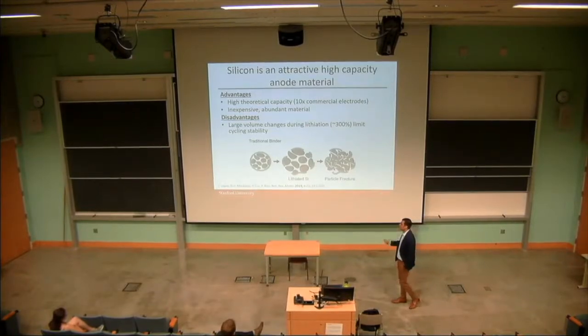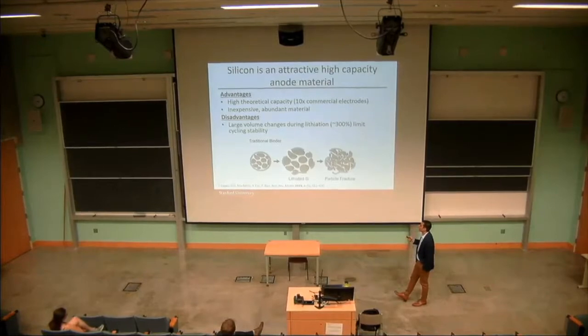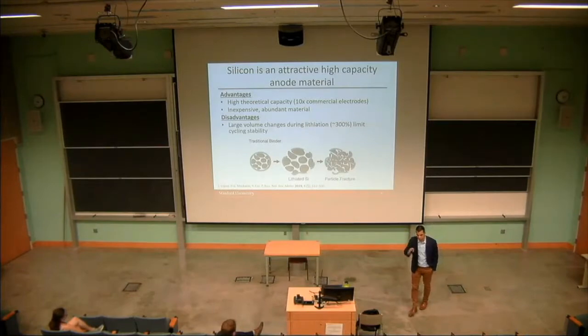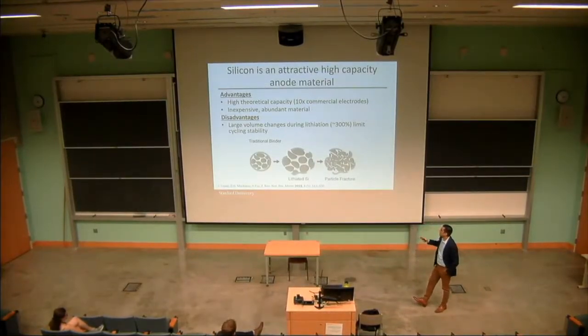Unfortunately, and the reason we're not already using it today in high quantities is because it has extremely large volume change. So silicon goes from just pure silicon, and it forms an alloy with lithium with about 3.5 lithiums per every silicon atom. But when it does that, it also goes through about a 300% volume expansion. And since silicon's not really an elastic or ductile material, it expands and then fractures. It's quite brittle, and it has anisotropic expansion along different crystal planes. And so what happens is when you lithiate the silicon, it will expand and then fracture, and then you end up having two main failure mechanisms from this fracture. The first is you have all of this new surface area of these smaller particles.